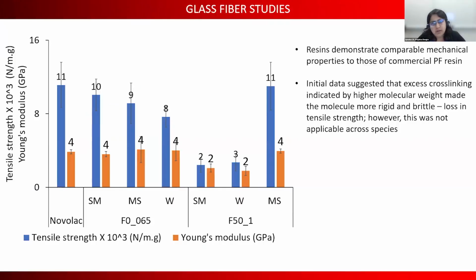Here I am showing you the tensile strength results of the glass fiber studies. And our initial preliminary screening showed that many of the resins that we prepared were quite comparable to the commercial Novolac resin. Phenol formaldehyde resins can be of two types. One is a Novolac, which is produced in acid conditions, and one is a Resol type, which is produced in alkaline conditions. Since we synthesized our resins in acid conditions, they were more similar to the Novolac type phenol formaldehyde than the Resol type. The commercial process for Novolac type synthesis also requires another crosslinker, HMTA, which I will talk about later in the slides.